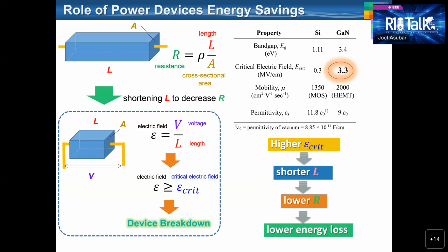This is where the so-called wide bandgap semiconductors like gallium nitride come into the picture. As we can see, this gallium nitride has almost 10 times larger critical field, EC, than silicon, which means that for the same breakdown voltage, a device made from gallium nitride can be made much shorter compared to a device made from silicon. And this leads to a lower resistance and therefore lower energy loss. So basically, this is the line of thinking of using wide bandgap semiconductors to obtain highly energy efficient devices.